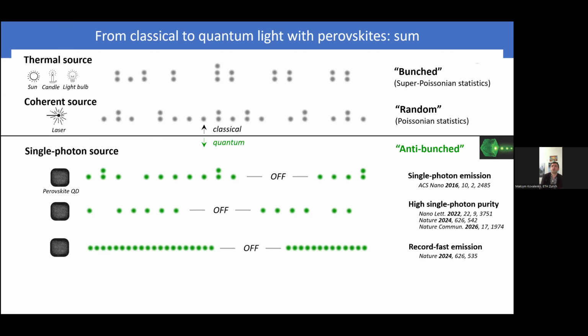Thank you. We do have a vision. We don't work much on that, but indeed, if you, let's say, have a local electric field, you expect some sort of Stark effect, for example, on your exciton. Or the same with magnetic fields and things like that. Indeed, they may be used as quantum dots, as local probes for temperature, electric fields or other fluctuations. Perovskites have a very strong temperature dependence, for example, anomalous compared to other semiconductors. So you could imagine sensing temperature as well. But the first step towards all these applications is to make sure you get a quantum dot which is stable for days and many months, so that what you observe is not just a compound effect of own degradation plus local effects, right? Yeah, but it's a promising direction. I agree. Yeah. Thank you.